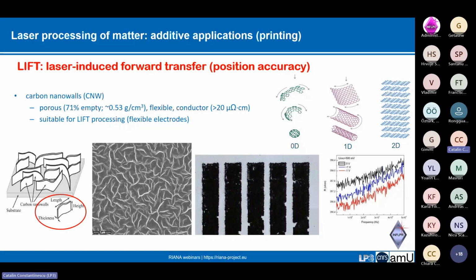This structure is a graphene carbon allotrope. So if we consider fullerenes as 0-dimensional, nanotubes as 1-dimensional, therefore graphene is 2-dimensional. Well, these graphene stacks, which are grown perpendicular to the substrate, transparent or not, are called carbon nanowalls. So they are empty, they're porous. So these carbon nanowalls combine porosity, conductivity, and flexibility. And with the help of LIFT, we preserve these properties, and we can therefore render them ideal for flexible electrodes.